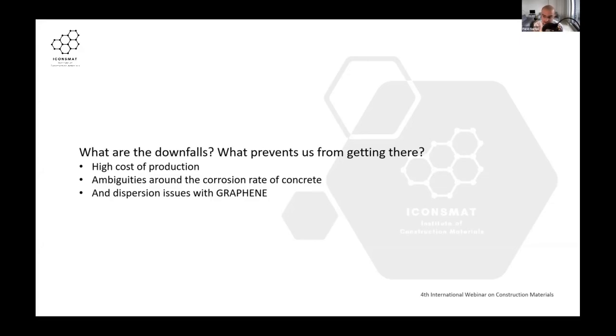Another problem with graphene when it comes to mixing in concrete returns to its hydrophobic characteristics. It just doesn't like to be mixed in water, which causes agglomeration, meaning that you will be seeing chunks of little black balls in concrete. And it's not good because you are expecting a continuous path for both electrical and thermal conductivity and not chunks of black balls. But remember, we have so far talked about graphene and not graphene oxide.